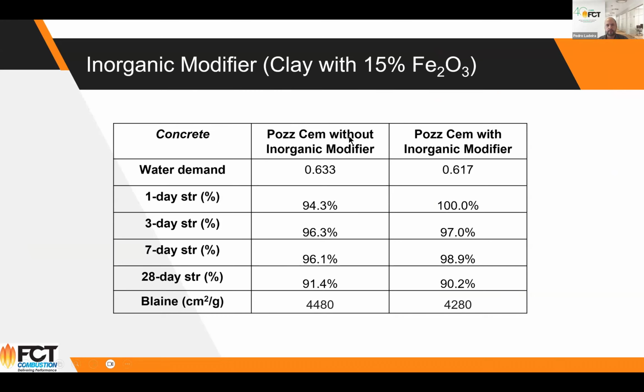And what we saw is that the loss, this is a relative loss in reactivity compared to the OPC. 1 day strength without the inorganic modifier was 94%, while with the inorganic modifier, we could get to the same result as an OPC for 1 day. For 3 days, we are better off with this. With 7 days, we still kept higher, and then it flattened out in the 28 days.